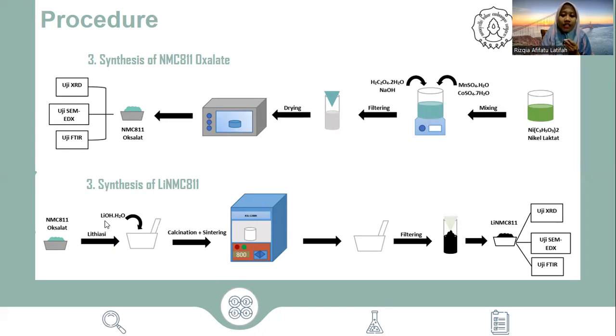After that, lithium was added to the nickel manganese cobalt. The material was mixed using a mortar and pestle, and then it was calcined at 500 degrees for 6 hours, and sintered at 800 degrees for 12 hours. Then the lithium nickel manganese cobalt was ground, filtered, and characterized.